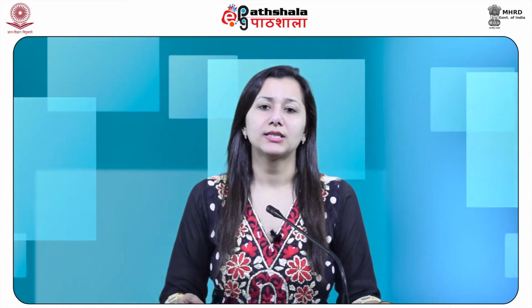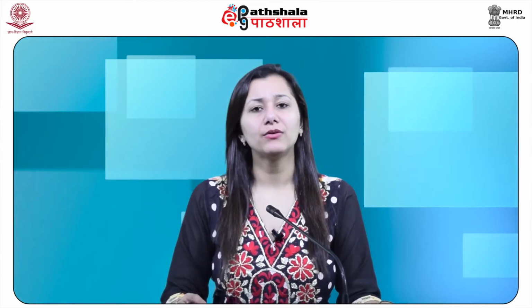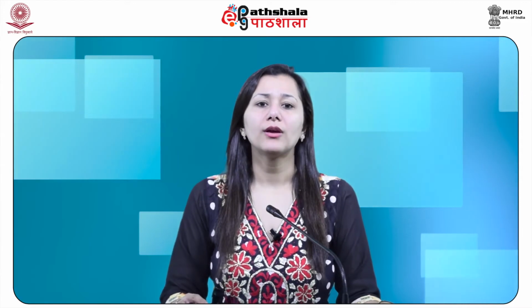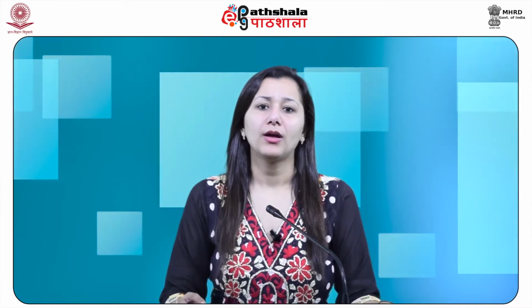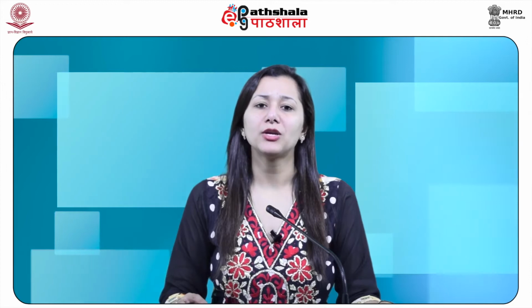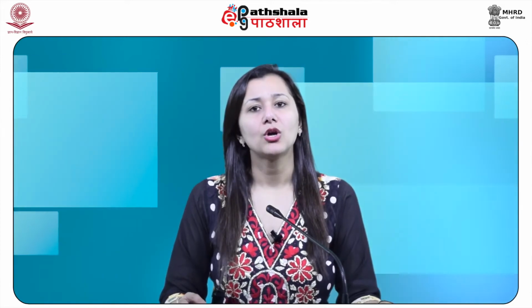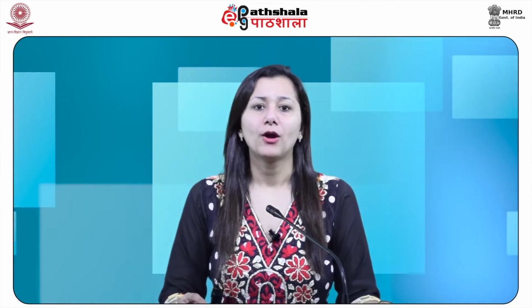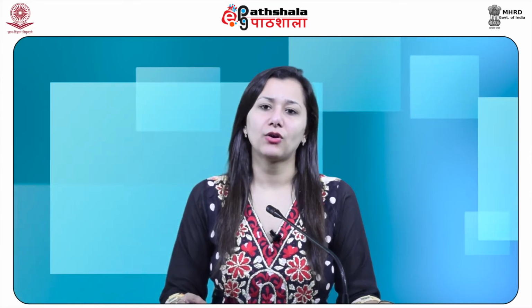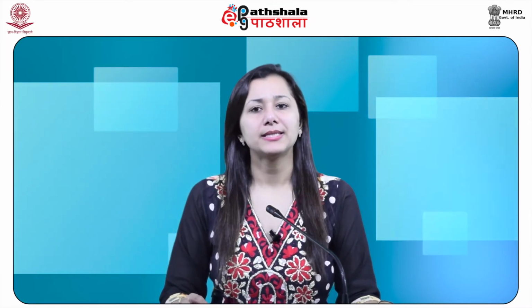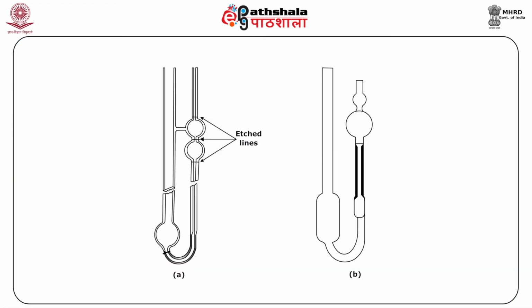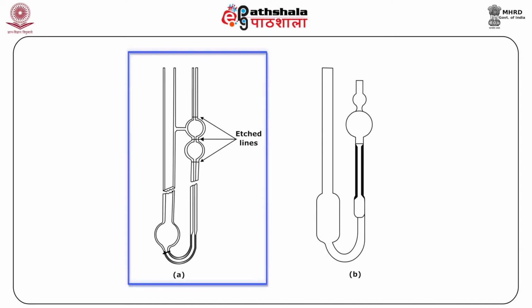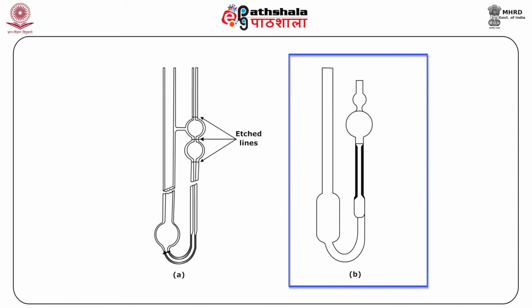Dilute solution viscosity is generally measured in capillary viscometers of the Ostwald, Fenske or Ubbelohde type. The latter has the advantage that the measurement is independent of the amount of solution in the viscometer. Moreover, measurements at a series of concentrations can easily be done by successive dilutions. The figure shows the capillary viscometers commonly used for the measurement of polymer solution viscosities. A is the Ostwald-Fenske viscometer and B is the Ubbelohde viscometer.